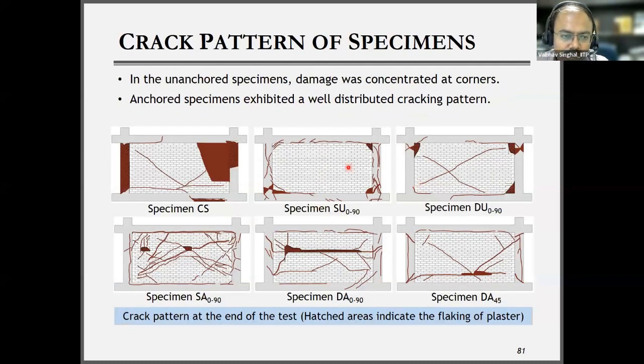So if you want to compare the failure pattern, for the control specimen, as you can see, some part of the masonry completely failed. It was coming outward. Now this is the response for the unanchored sandwich technique. So you can see there was no damage in the masonry wall. Most of the damages were seen in the frame and at the interface of the frame and the wall. Similarly, the direct unanchored has performed slightly better than the sandwich unanchored, but again, the masonry had minimum damages. Most of the damages were concentrated at the corners or at the interface of the masonry and the RC frame.